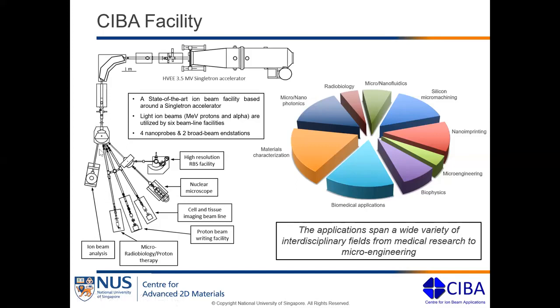Now I'll start from the left and describe a little bit what studies we do with these beam lines. From the left, we have the ion beam analysis beam line, where we can do Rutherford backscattering spectrometry, and then PIXE, which is particle induced X-ray emission. Both of these studies are related to compositional analysis of materials, or you can measure thin film thickness. PIXE can be used for finding trace amounts of elements inside your samples.